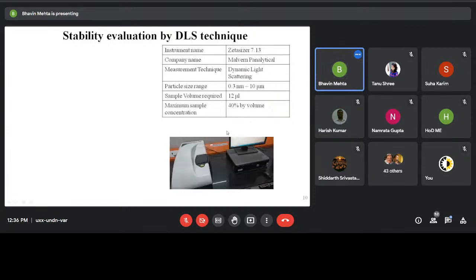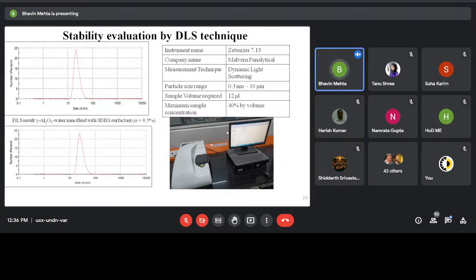And for that, we found the results like the average particle size in the tested fluid was found to be 24 nanometers with the fluid synthesized with the surfactant SDBS, and the volume fraction is 0.5%. Similarly, the average particle size was found to be 28 nanometers, which is quite near to the particle size of the nanoparticles, that is 20 nanometers. So we can say that there is no such agglomeration and sedimentation, and the fluid is stable, and it shows good stability at the end of the fifth day.